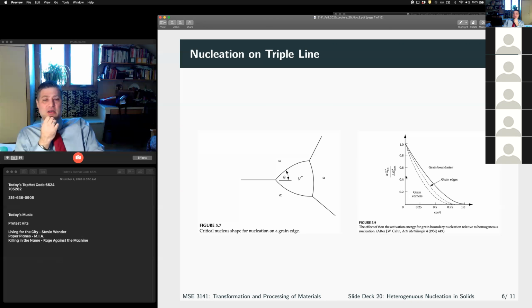if we reduce delta G star by half, remember that our nucleation rate is exponential, right? It goes by our Boltzmann statistics. So a 50% reduction in delta G star is huge. So if we're in a regime where we have this, guess where all the precipitates are going to be? On grain boundaries. There's no way you're going to get homogeneous nucleation when I've got a factor of 2 reduction. And that factor of 2 then goes into an exponential equation.